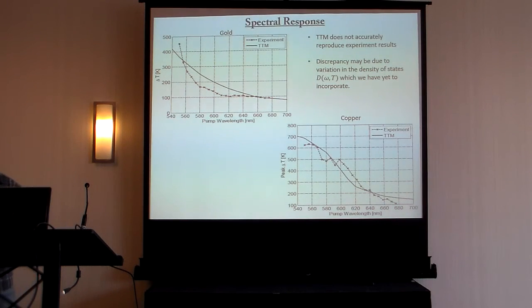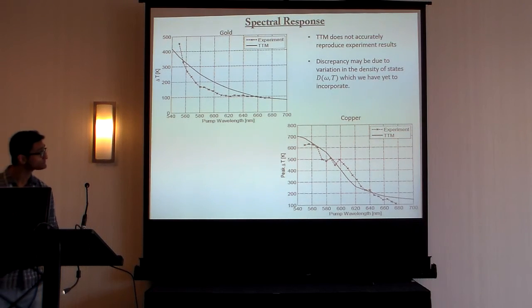Lastly, I'd like to talk about the spectral response of the change in electron temperature over the visible spectrum. And what we found is that we have qualitative agreement of the change in electron temperature over the visible spectrum. As we go to lower wavelengths, we do see an increase in the change in electron temperature due to a decrease in the optical penetration depth of the pump into the material. However, we do find discrepancies which we believe are due to the change in density of states, which we have yet to incorporate into our model.